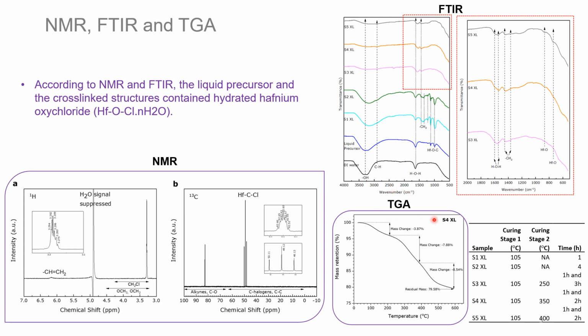Now, TGA of one of these cross-linked samples was performed in the presence of air, and three mass loss regions were observed at temperatures below 600 degrees C. This mass loss was attributed to the release of evolved gases such as water vapor and volatile gases, for example, carbon monoxide, carbon dioxide, methane, and chlorine.